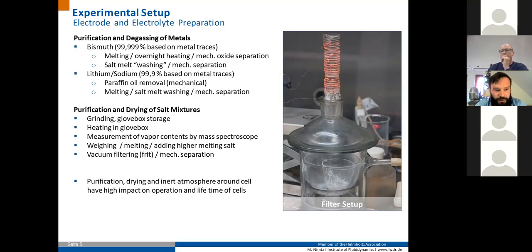Then after drying, the preparation of the eutectic mixtures is done by weighing, melting, and then adding the higher melting salt to create the mixture, the low melting mixture. And last steps are, for example, vacuum filtering through a ceramic frit to also remove unwanted impurities, hydroxides, and similar. Here also a mechanical separation, manual scratching the solid salt surface to remove impurities, is possible.